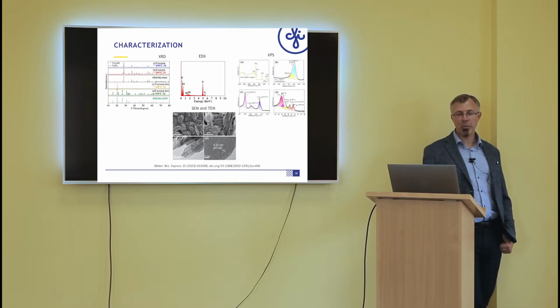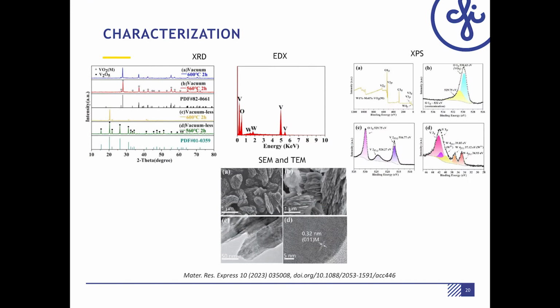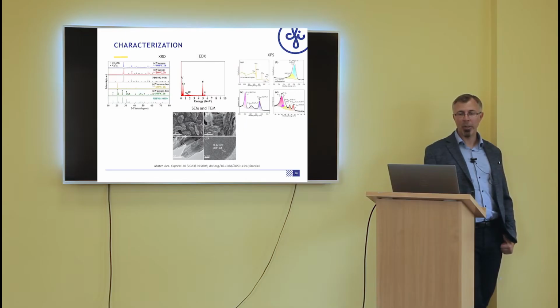X-ray diffraction can be used to see how crystalline vanadium dioxide is and to exclude presence of other oxides like V2O5. EDX can be used to measure amount of dopants, tungsten in this case. XPS can be used to probe valence state of vanadium. Scanning and transmission electron microscopy allows to see morphology of obtained nanomaterials as well as their crystalline structure.